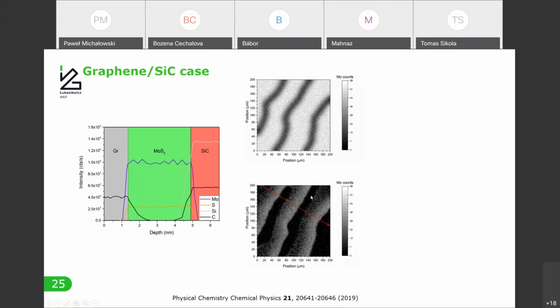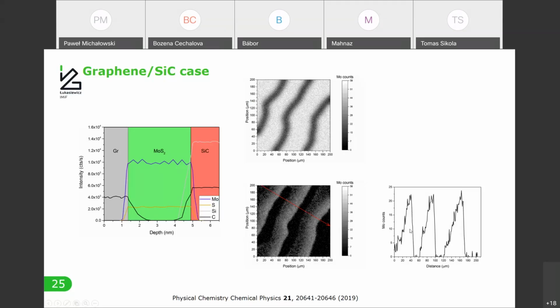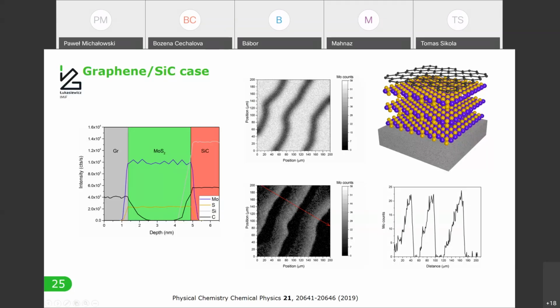symmetrical, the molybdenum that we find on the silicon carbide interface is not symmetrical at all, but you can see here is the line scan, so there is a very sharp interface in one case and a clear diffusion in the other. That simply means that this step here is higher than this one, so when the molybdenum is intercalating here, it can only diffuse along the terrace in this direction. But again, the final result is that actually in this case we can grow the molybdenum sulfide film below graphene layer, which was kind of surprising.